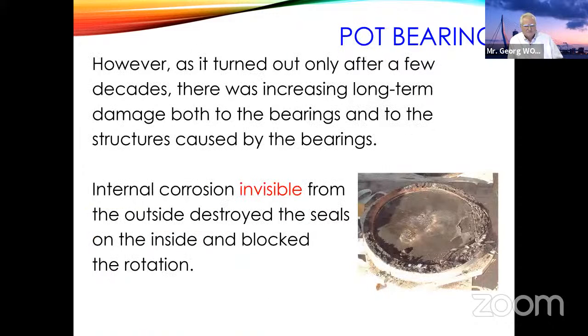But after some decades, not years, really decades, we found an increasing amount of long-term damage to the pot bearings caused by corrosion. The problem is the internal corrosion is invisible from outside, and when the bearing is moving, it destroys the seals on the inside, and sometimes the corrosion is so heavy that it blocks the rotation of the bearing.